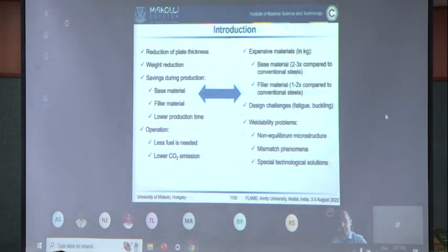So this high yield strength, because in the area of mechanical engineering, in most cases, we design the structure based on the yield strength. If it is a clear tensile loading, we can fully use the advantage of high strength steel. But if it's, for example, compression stress or fatigue or buckling of the structure, in that case, these high strength steels are not as advantageous as we would expect. So there are always challenges in deciding which part of the structure should be produced from high strength steel.